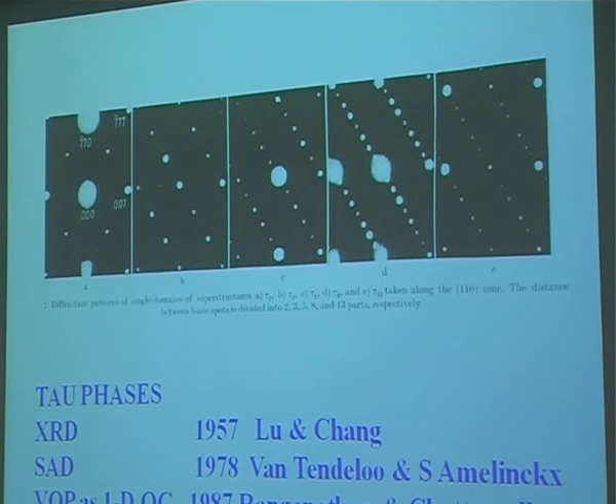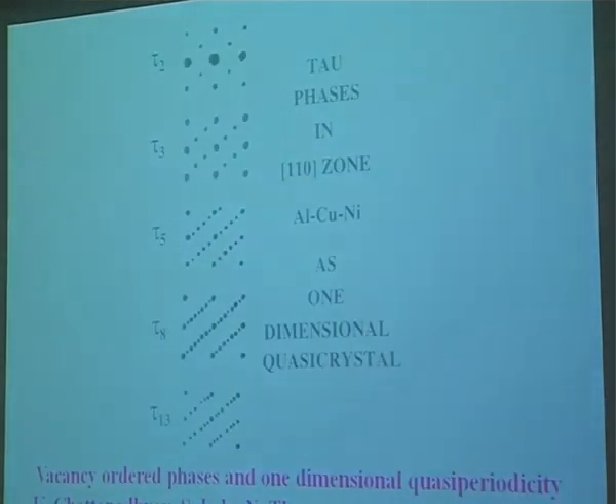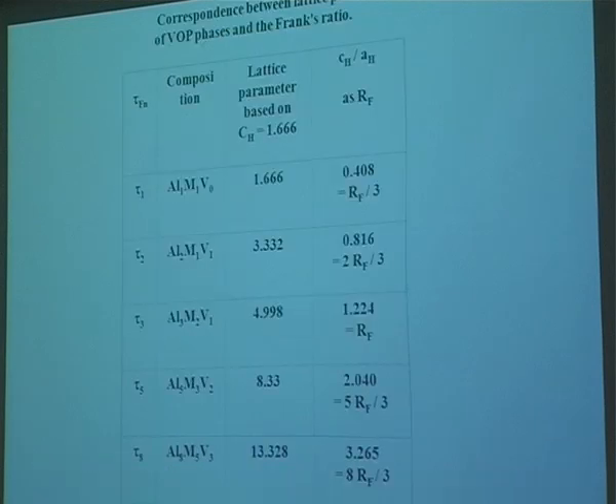This is an important work that we have done from the Indian scene, that by just looking at this pattern, we didn't produce this pattern, we looked at this pattern. We said these are just like we have a 3-dimensional icosahedral quasicrystal, a 2-dimensional decagonal phase, we have a 1-dimensional quasicrystal. And we did, this shows the same pattern in terms of schematic form, 2, 3, 5, 8, etc., published in Acta Metallurgica in 1987.